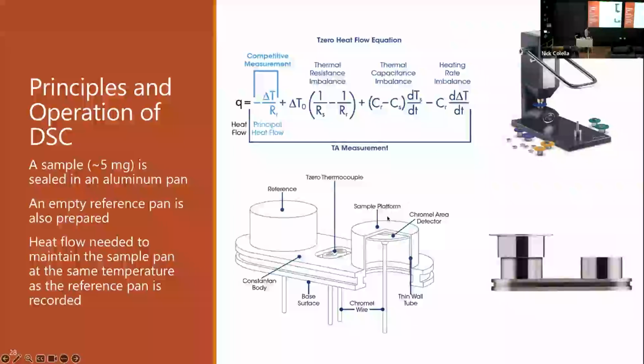And so it's DSC, differential scanning calorimetry. The D is for differential because we're going to have an empty pan on one post and then a pan with your sample on the other post. And the measurement is how much more energy do we need to put into your sample to keep it at the same temperature as an empty pan. So all that energy is going into your sample. If you have to melt something, you need to pour in even more energy. And we can look at the heat capacity as a function of temperature as well. The S is for scanning because we're scanning our temperature, and it's calorimetry because we're putting in energy and measuring temperature.